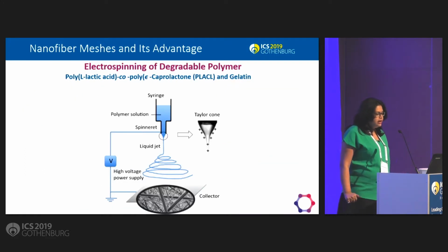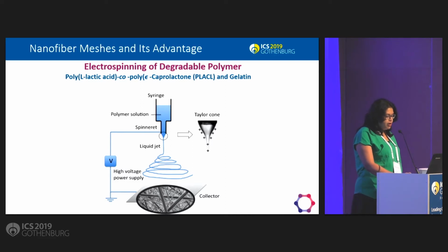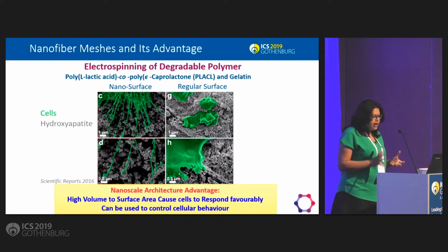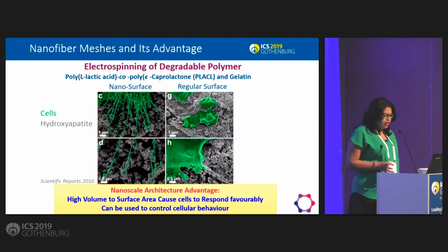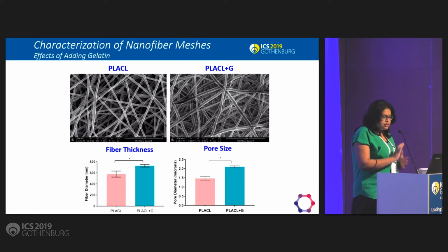We use a technique called electrospinning, where we use a polymer which is a copolymer of PLA and PCL, combining it with gelatin. The reason why nanofabrication is extremely attractive is that it gives a high surface area compared to the volume, and the cells interact much better, which you can see as they produce these nanoscale filopodia to interact with the material. So we hope that this will lead to a better, more desirable foreign body response.